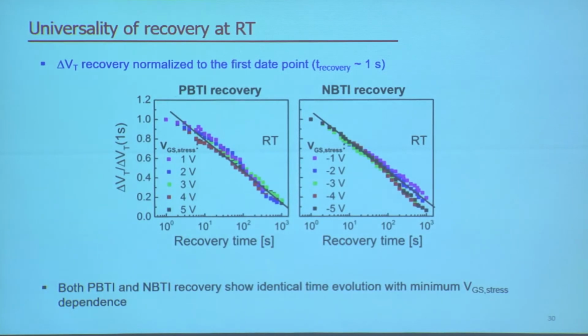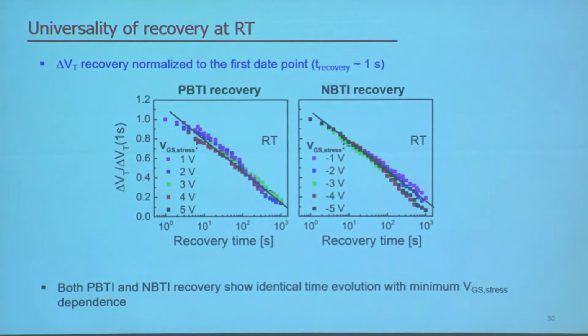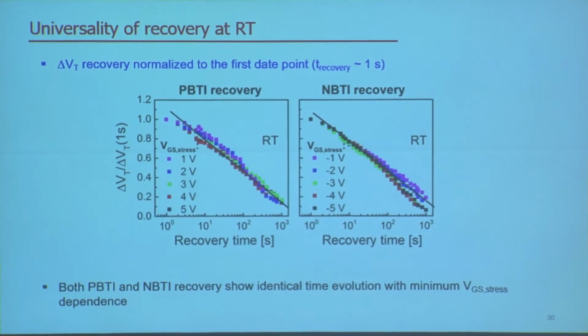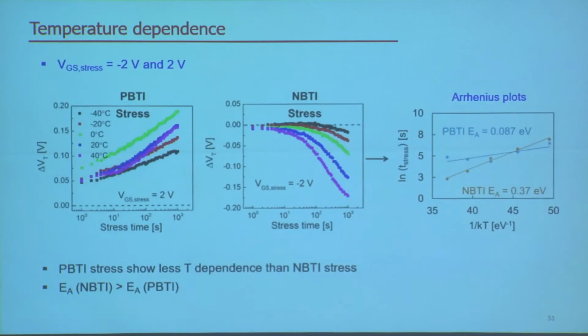So we talked about mostly the stress regime, and now let's look at the recovery, which gives us more insight on what's happening behind the BTI. So what we do here is normalize all the recovery data to the first data points and look at the recovery. And we see that they overlay on top of each other very well despite the difference of stress voltage for both PBTI and NBTI, and they have the same slope, the recovery rate.